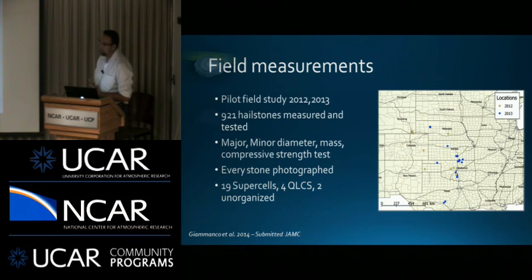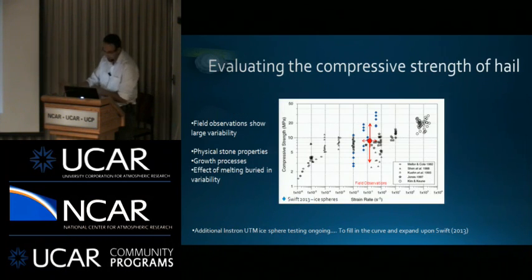So we essentially try to make a decent forecast that we'd have some severe weather. And this is a plot I quickly threw together because I haven't had a chance to make a really good one compared to the historical work. I added in here a recent study by Swift in 2013 that was looking at pure ice compressive strength tests, and that's the blue dots. Everything else is based on ice cylinders and other evaluation of the compressive strength of ice grains, and that's what the curve looks like. You can tell the Swift study had some variability, and I just plopped on there our field observations, and that's generally representative, plus or minus a standard deviation from the whole group. So it actually fits reasonably well with what you'd see, with the observed variability there, with regards to pure ice.